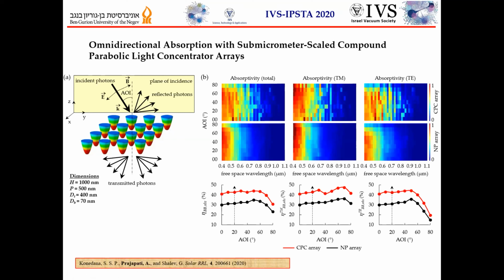Broadband absorption efficiency of TE decreases significantly for AOI greater than 50 degrees, whereas broadband absorption efficiency for TM retains omnidirectionality up to an angle of incidence of 70 degrees. Similar responses are also recorded for the nanowire, which is in black, and the red one is the CPC array.